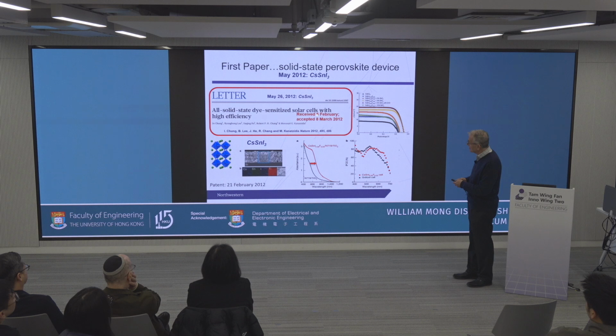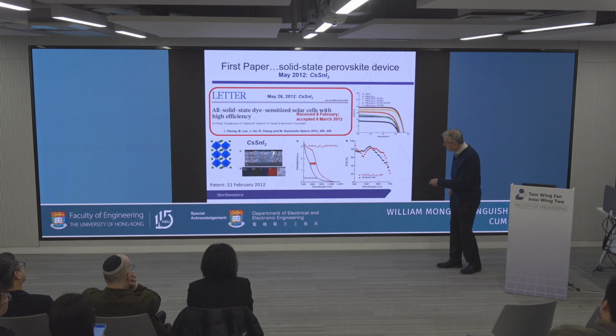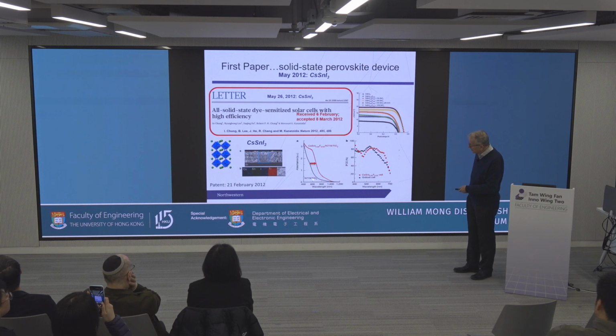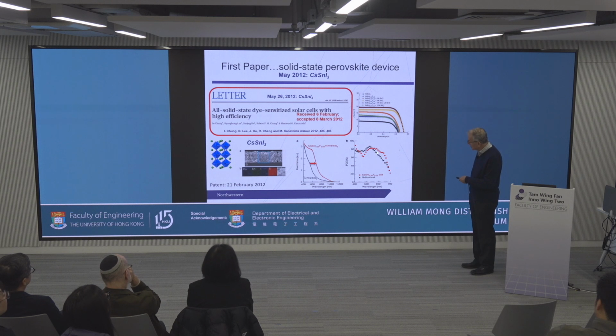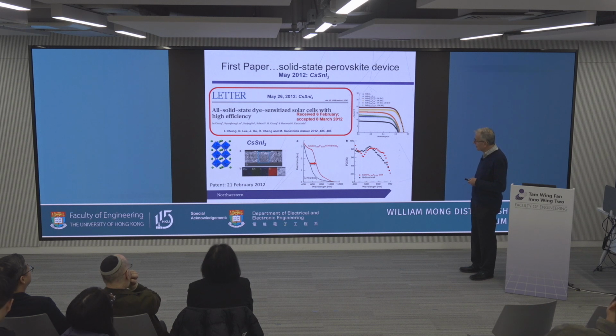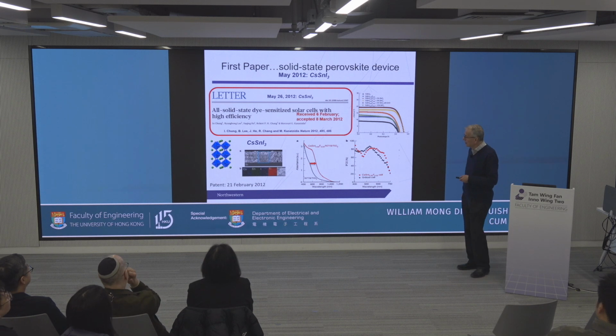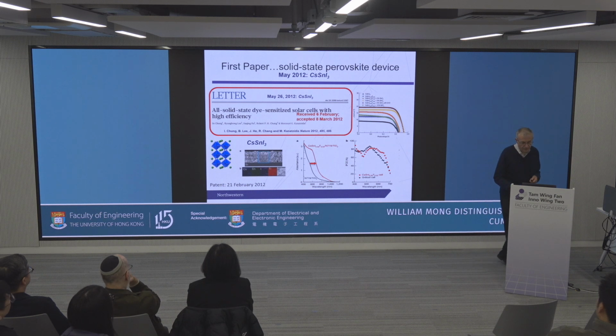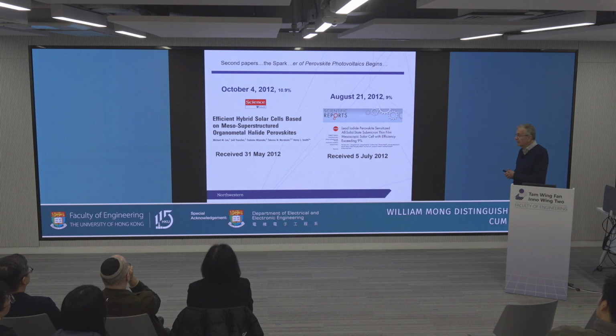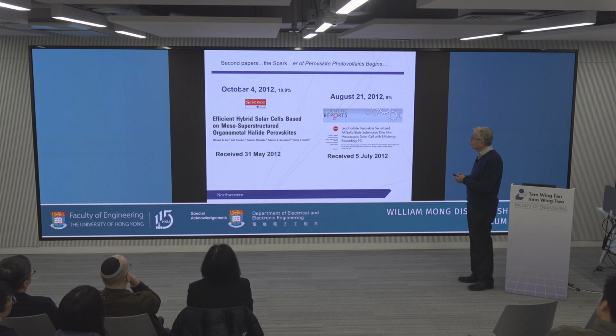We submitted it February 6, it was accepted in March, and it was published in May. And this is the spectra we put in there. This is absorption spectra. The black is just a standard Grätzel cell. And here's our spectra. You see the redshift. Also, the EQE spectra shows excess efficiency because of the perovskite contributing to the performance. And so this came out, we filed the patent in February 21. So it made a big impression. People noticed, they were excited about it. Efficiency was 10%.